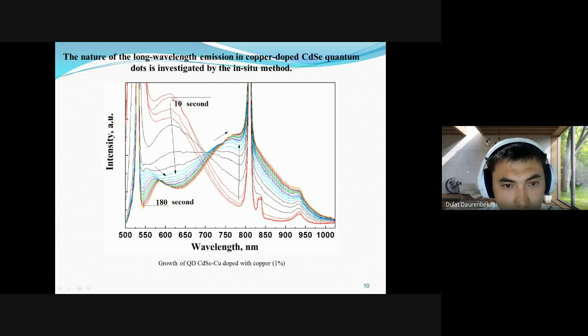At this point we add the copper precursor, or copper impurities, and you can see what process happens: the host luminescence, or band gap luminescence, starts to decrease, and at this time the impurity luminescence increases. Host luminescence decreases and impurity luminescence increases. You can clearly see it on the figure, and this is the last measurement at 180 seconds, and the majority of the luminescence comes from the impurity. It's for 1% of impurity.